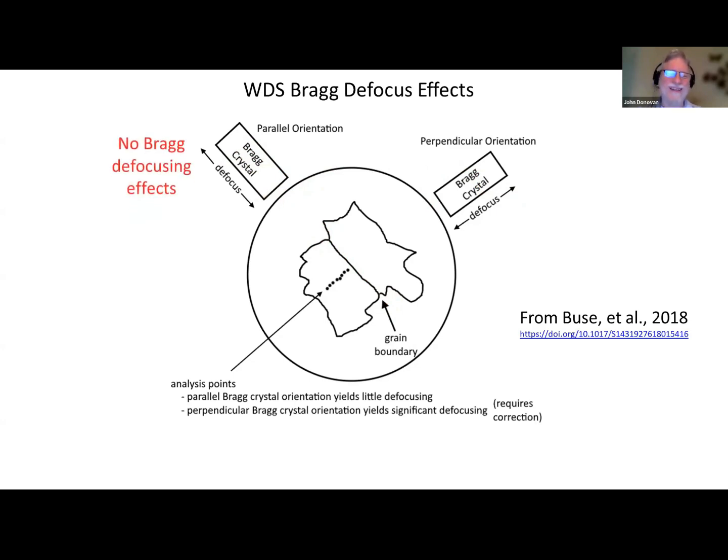Excuse me, abort, reset. If you're in this orientation, then as you move in this direction, there's no defocusing. But if you're looking at this crystal and you move away from that crystal that way, you are going to get defocusing effects. And Buse published a really nice paper about this in 2018.